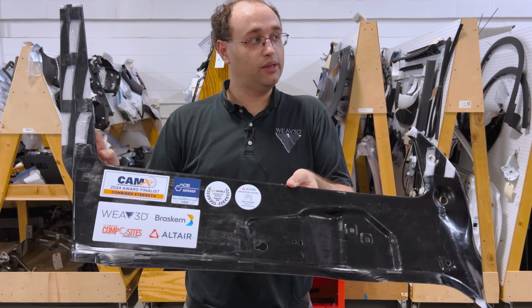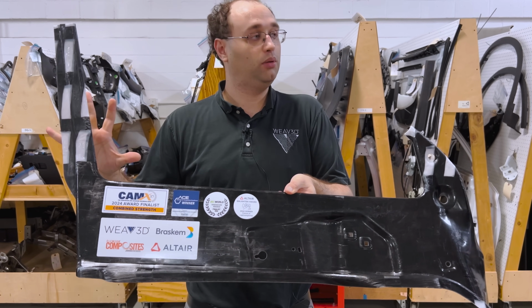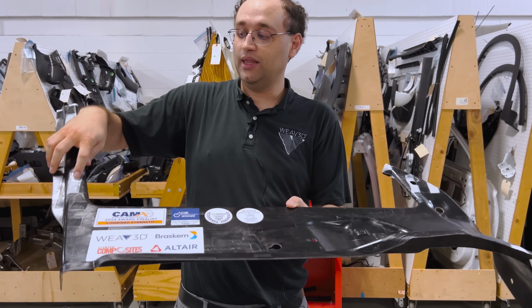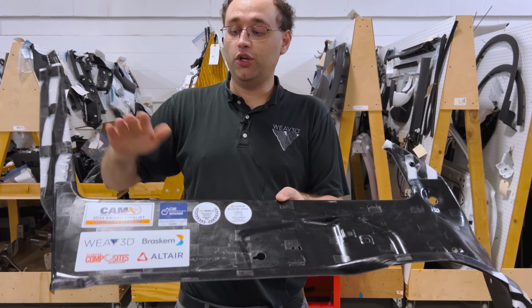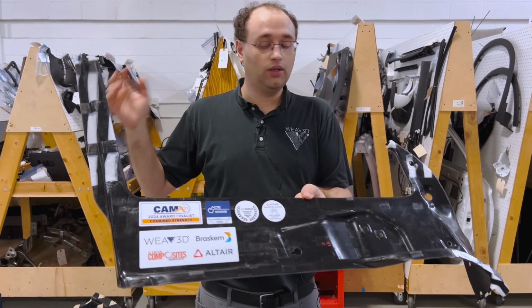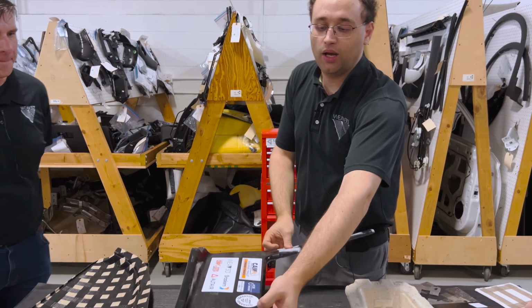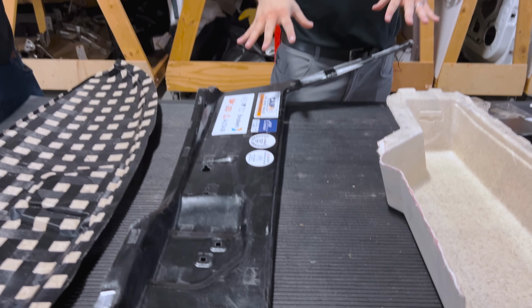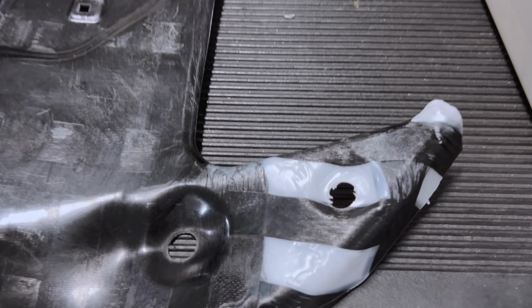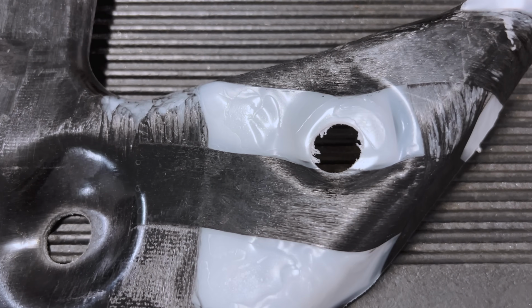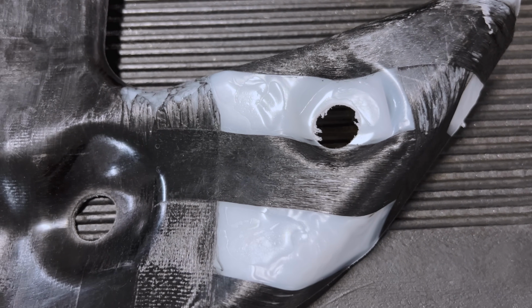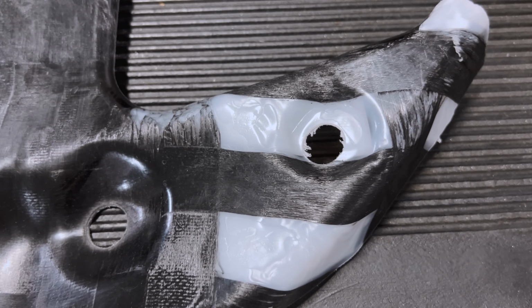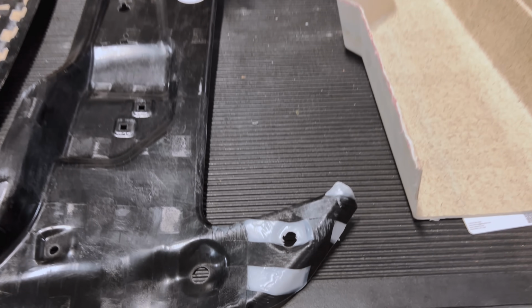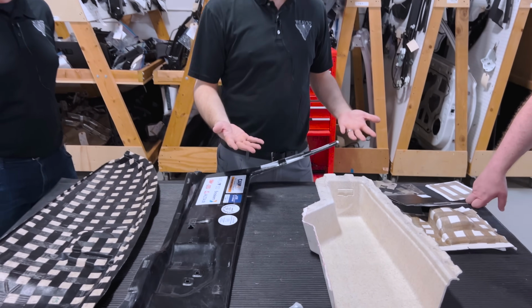So this white that you see here is actually just the polypropylene showing through. There's no tape in these opening gaps, so you're not paying for this material. And what we found was we were about half the cost of the carbon fiber organosheet, and we had 63% less trim scrap by weight, because we weren't paying for all this material that had to get cut off. It was basically just polypropylene, and polypropylene is cheap.